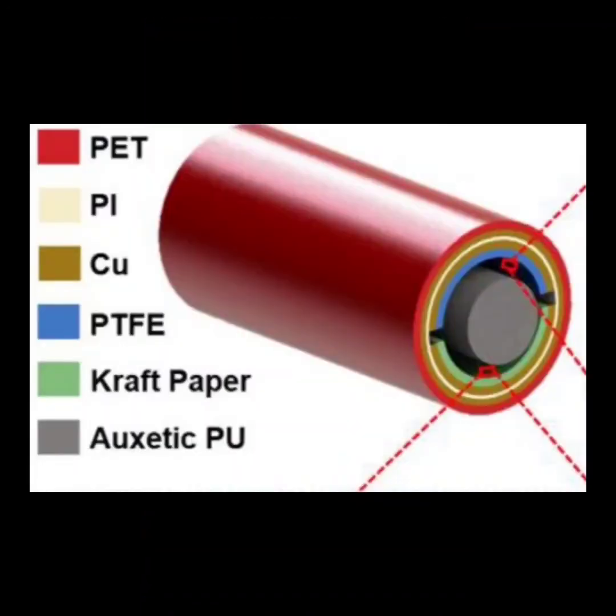This is the APU tank schematic structure. The APU tank is composed of a cylindrical auxetic PU foam and an outside shell. In order to fabricate the foam, PU foam was repeatedly and gradually compressed in an aluminum mold, heated and cooled down. The cell ribs of the PU foam were compressed simultaneously in 3 dimensions to buckle and produce a reentrant structure, which resulted in the auxetic property.